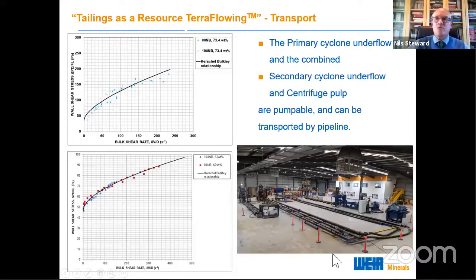When we do the test work in the test facility, that you can see in this area below, we pump these products through the tailings pipelines and measure the pressure gradients and the losses. We're able to develop these relationships that allow us to design pipelines and size pumps, and the type of the pump needed to deliver these products over distance. So depending on the distance would determine whether you would require a centrifugal pump or positive displacement pump. So all of these products that we're producing through this Terraflowing process for mine sites can be pumped with some form of Weir pumping system.